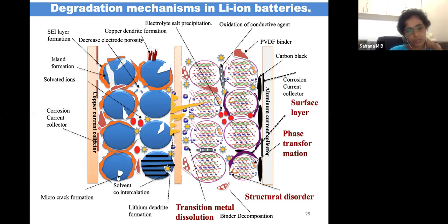In addition, the copper current collector can also corrode. The binders can separate out, and there can be island formation. That is, some portion of the material may not come in contact with, or will not be involved electrochemically in, the subsequent cycles. Or in the case of the cathode, the transition metals can dissolve in the electrolyte.